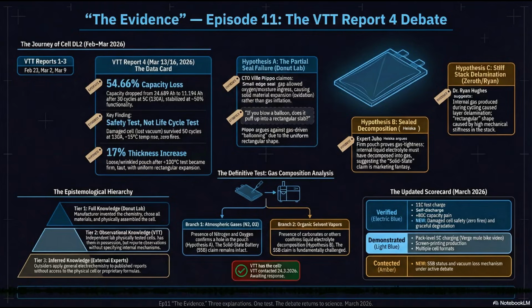Because gas pressure pushes equally in all directions against a flexible membrane. Right, it seeks a spherical shape. Precisely. Piippo's argument is that if gas were filling a sealed pouch, the flexible aluminum laminate would bow outward. The fact that the cell remained a flat, rectangular slab indicates that the solid stack of electrodes inside was literally growing thicker layer by layer due to oxidation, uniformly pushing the pouch walls straight out.